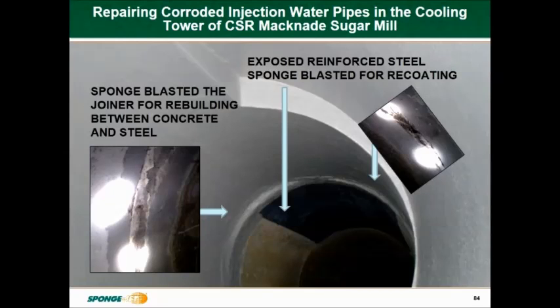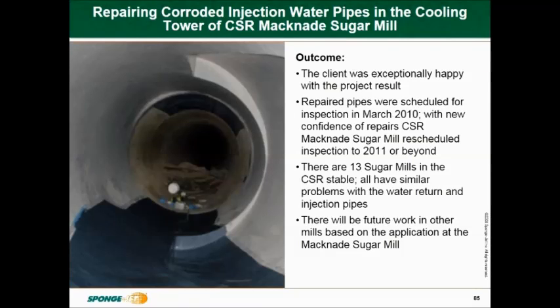There were issues with the exposed rebar in the concrete pipe. It had eroded away. It was blasted back to the original state to an SA3, then rebuilt with Belzona quartz and overcoated with 1341. The client was very happy to see the finished result, and the pipeline was inspected 1 year later, and found that there was no damage to the repairs and maintained its design integrity.